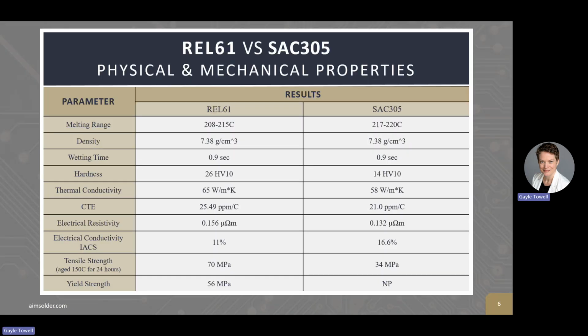This is just a brief overview of some of the physical and mechanical properties of REL61 compared to SAC305. Again, you can see the slightly lower melting temperature, very similar density and wetting time, but it has a higher hardness. Thermal conductivity isn't significantly different. Many of the other properties are somewhat similar, slightly lower conductivity, but much improved tensile strength after aging.